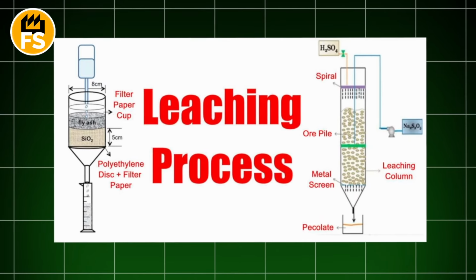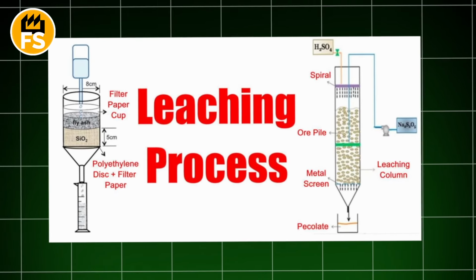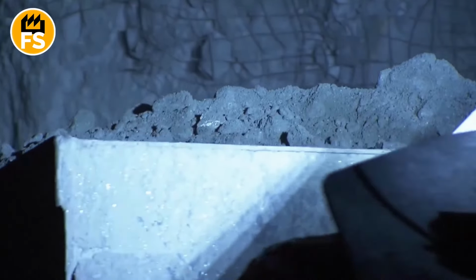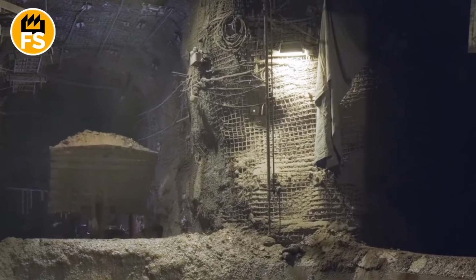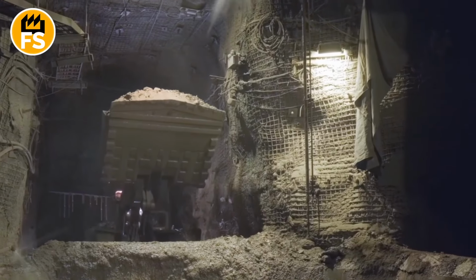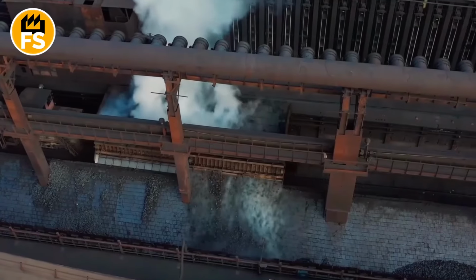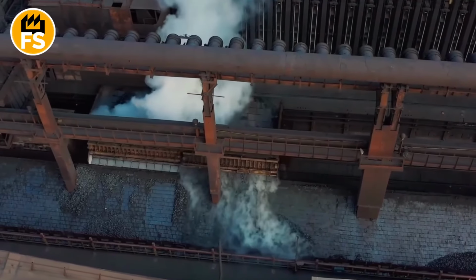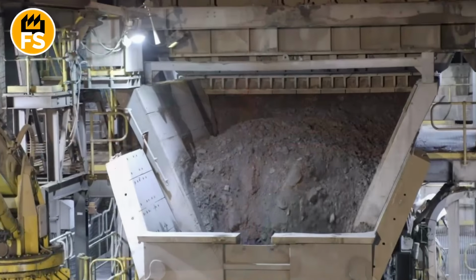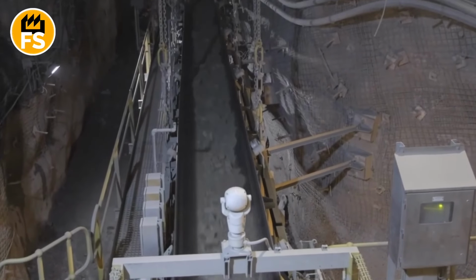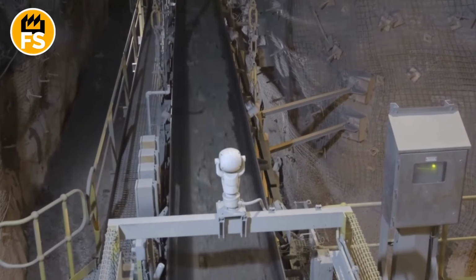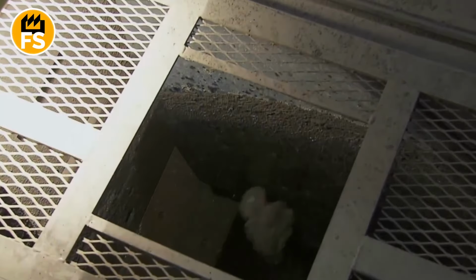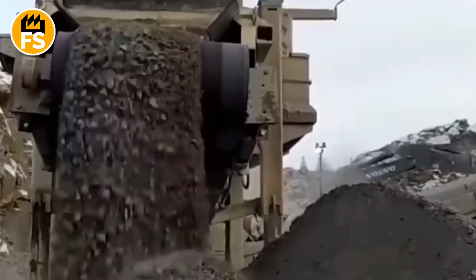And now the real chemistry begins, a process called leaching. This grey sand is mixed with water, forming a thick pulp, and pumped into huge vats, the size of a small house. A powerful chemical solvent is added to these vats, most often sulfuric acid. This acid, like a hungry predator, begins to eat the uranium, pulling it out of the solid rock and turning it into a liquid, dissolved state. This process lasts for many hours, while the entire mixture is continuously stirred.